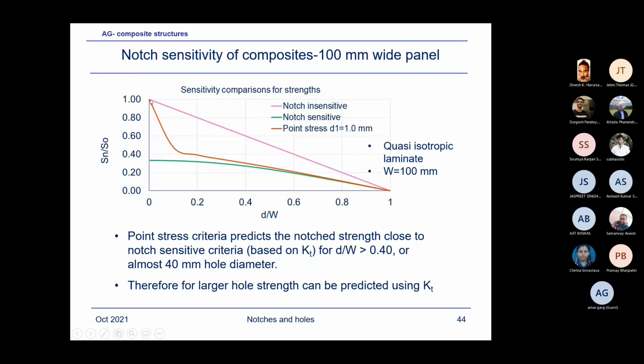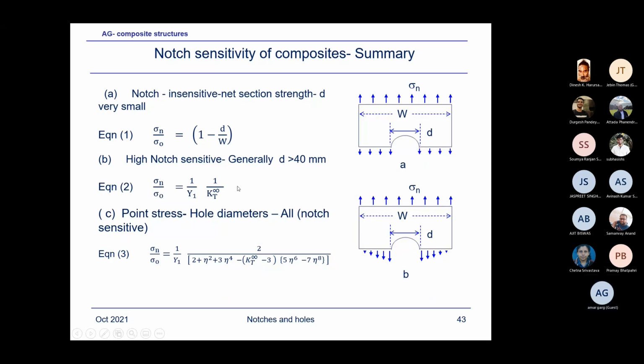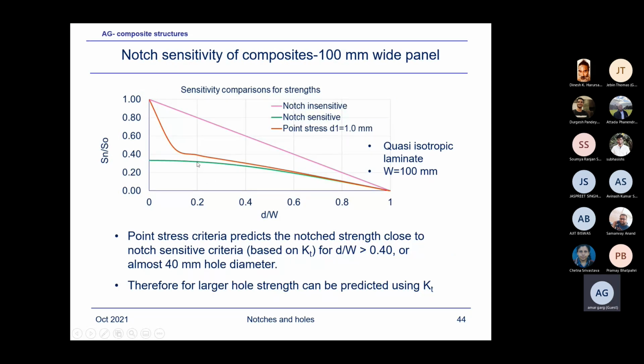And here, what you see, this one is based on the point stress criteria for the residual strength, and this is based purely on the stress concentration factor, 1 upon kT. Why you are finding this d by w effect is because the hole is increasing in size compared to the panel width, and this variation is coming due to the parameter Y, which is the finite width correction factor. If this is an infinite panel, then what you will find is like this one here, where you have a very large panel and the hole is smaller.